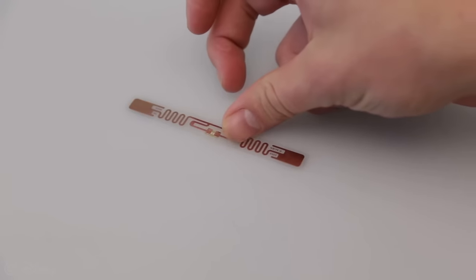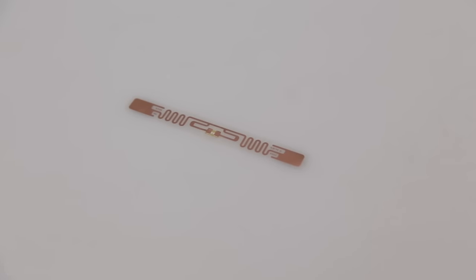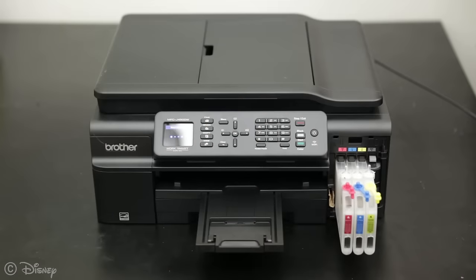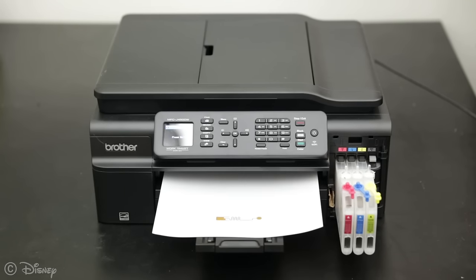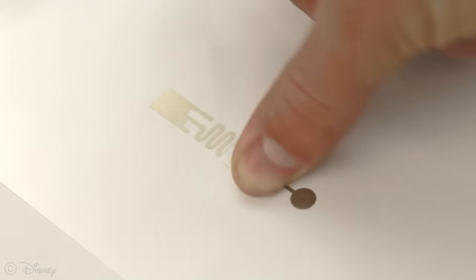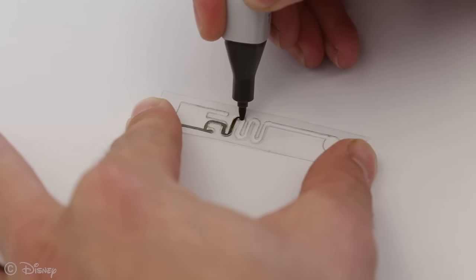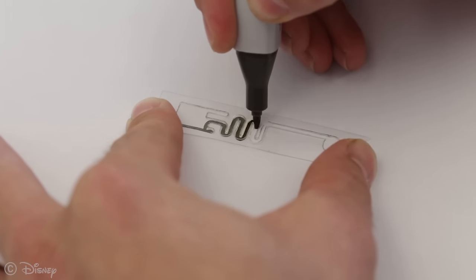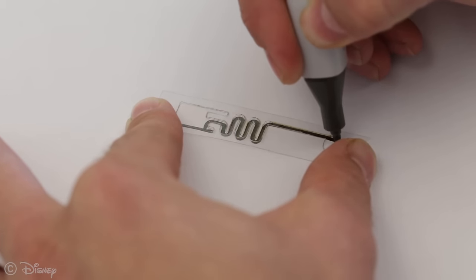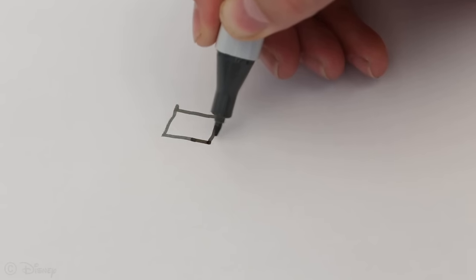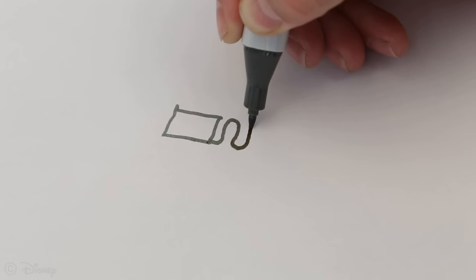We use sticker-like, off-the-shelf RFID tags with an embedded antenna and RFID circuit. We print antennas using silver nanoparticle inks from an inkjet printer and add a small sticker with the RFID IC. Similar to the printed tags, a conductive ink pen is used to trace custom tags through a stencil. A pen can also be used to draw freehand antennas.